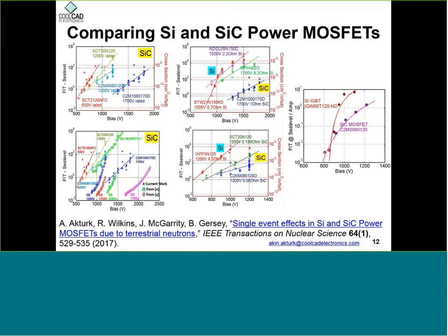In silicon, what people do is they generally derate the part so that a certain FIT number is achieved per device. So when the system is deployed, the total FIT number is below a certain value. So in small, medium applications, the total FIT number can be about 1, but in a large application, it can be like 10 or 100. And also for aerospace applications, you want low FIT numbers, so the lower the better. So you don't have any device failing or system failing due to one of these devices failing.